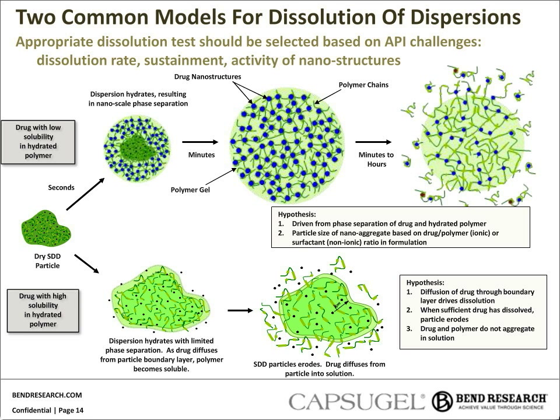So the first model: commonly if you're working with a dispersion, you believe that you have a low water solubility drug. And that brings the formulator to a dispersion, so we're really thinking about low solubility in water or in a hydrated polymer situation. As we go across the top of this diagram, we're seeing a dry SDD particle hydrate and then form some nanoparticles. We think of this in two different ways: either as association of the drug with a hydrophobic polymer patch, or that the hydrophobic drug is now being capped by some piece of the polymer.